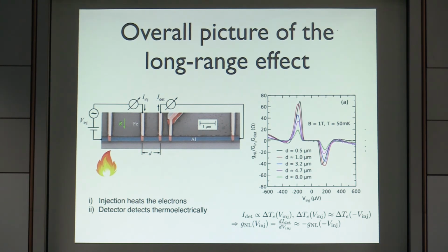The inelastic scattering lengths are actually quite long. So this meant that this superconductor was heated over a long distance, and that created a temperature difference across this detector contact, and that temperature difference actually drove a thermoelectric current. And this was actually what was measured here. Therefore, the relaxation length that was measured here was not a spin flip relaxation length, but rather an inelastic scattering length. In fact, we don't fully understand why it was so short.